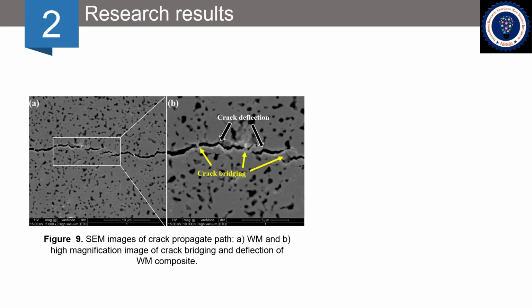The propagation path of indentation cracks in WM composites was shown in Figure 9. Since fracture toughness is related to crack growth resistance, crack growth path analysis is a valid way to discuss the crack growth mechanism. Crack bridging and crack deflection in the crack propagation path can be found in the WM composite in Figure 9b. When the crack encounters magnesium oxide, the obstruction effect of magnesium oxide will change the direction of the crack propagation path.